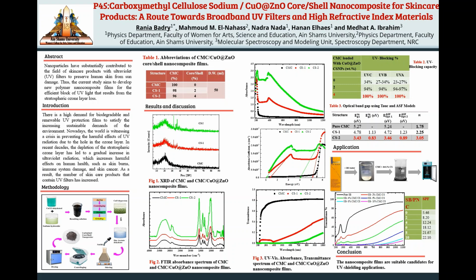Accordingly, the aim of our study is to prepare a polymer nanocomposite based on CMC and copper oxide zinc oxide core shell for the efficient block of UV radiation. Thus, we prepared the core shell nanoparticles as presented in this figure using the precipitation method, and then we added different weight percentages of the prepared core shell nanoparticles to the CMC solution using the casting method. The XRD results confirmed the amorphous nature of the prepared polymer nanocomposite due to the appearance of the broad peak at nearly 2 theta equal 20 degrees.